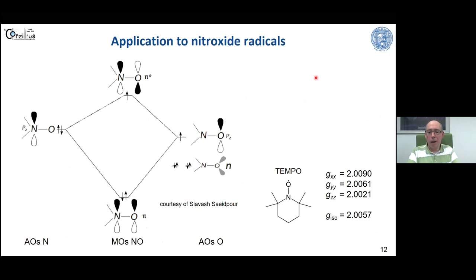All right, you can also apply this to radicals, for example, to nitroxides. And this also explains why the tempo radical, for example, has a deviation from the free electron g factor, which would be 2.0023. And the largest deviation you can see here is in the g_xx direction.